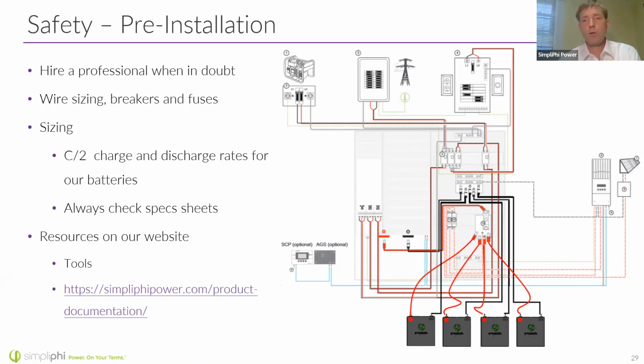The capacity divided by 2 means you can charge the battery up or fully discharge the battery in 2 hours, and we typically specify this in an amperage, right? So if we have a 75 amp hour battery like our Phi, and you take 75 amp hours, you divide by 2 hours, you get 37.5 amps. Okay, so that's our charge and discharge rate for that battery. We always recommend a C/2.